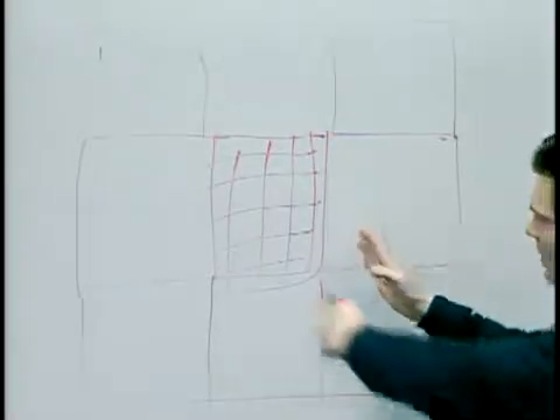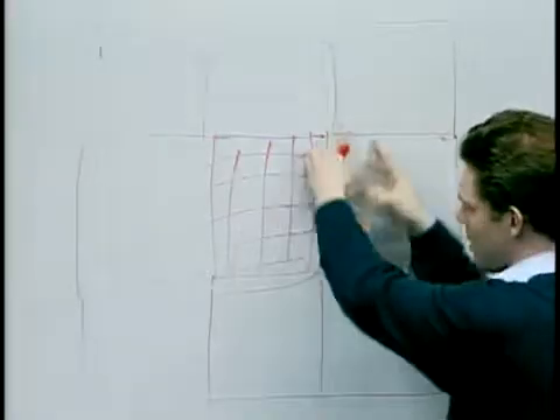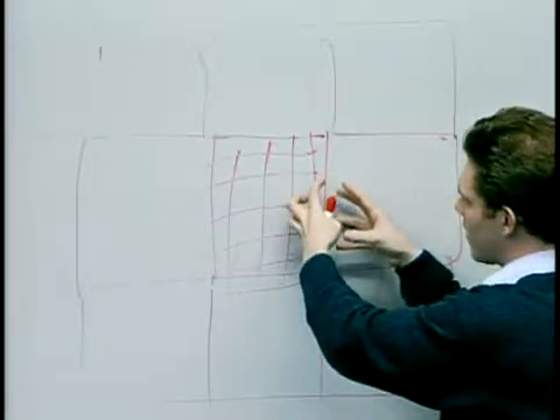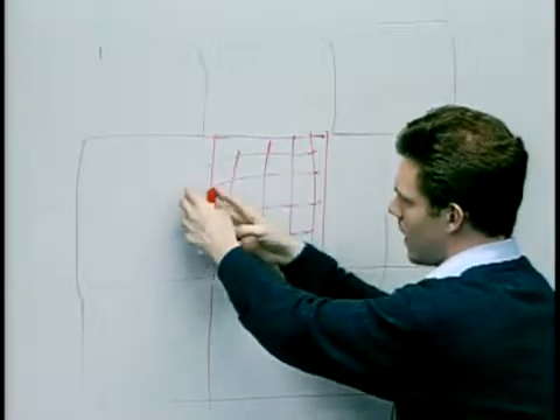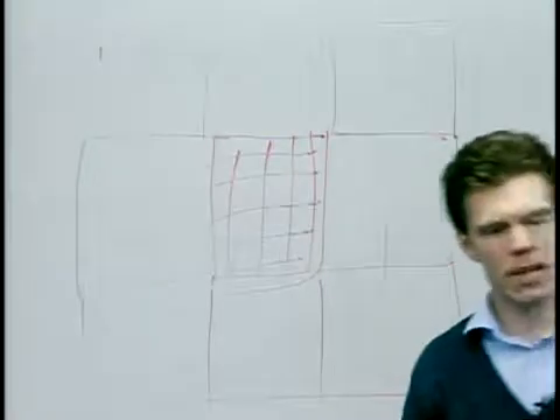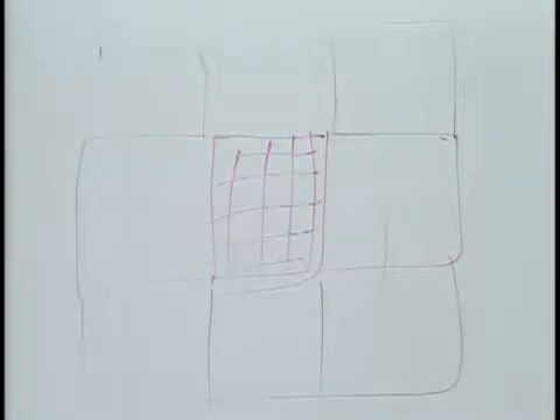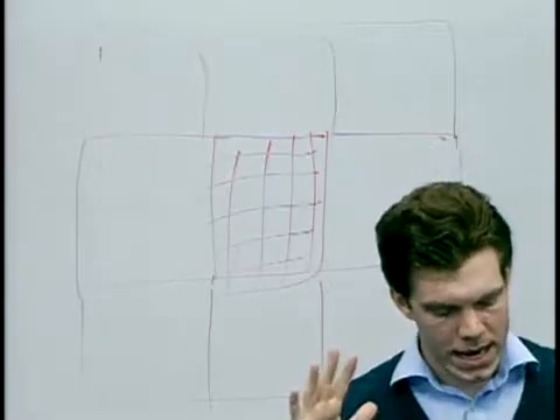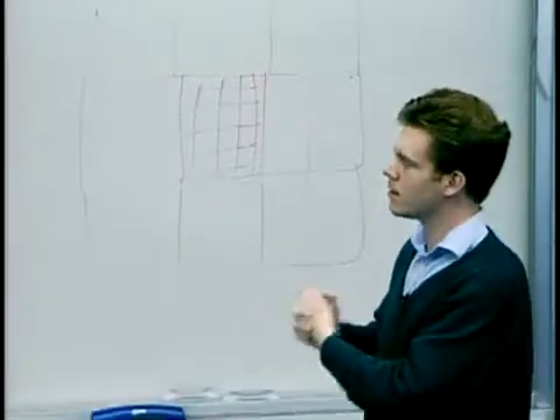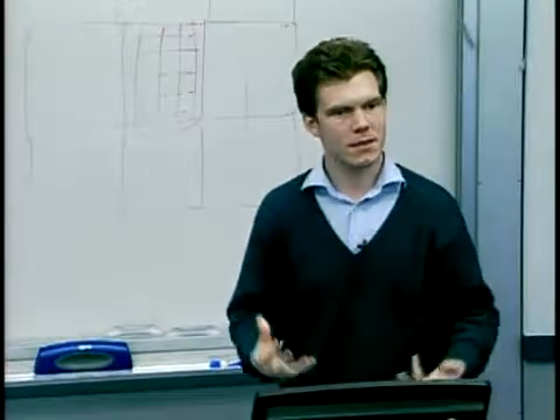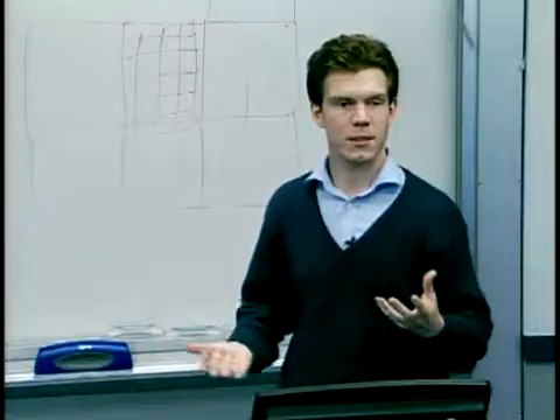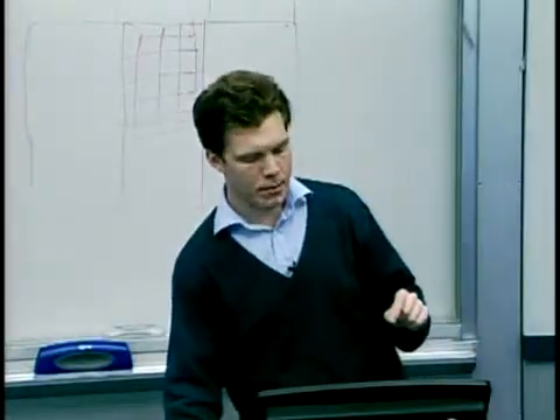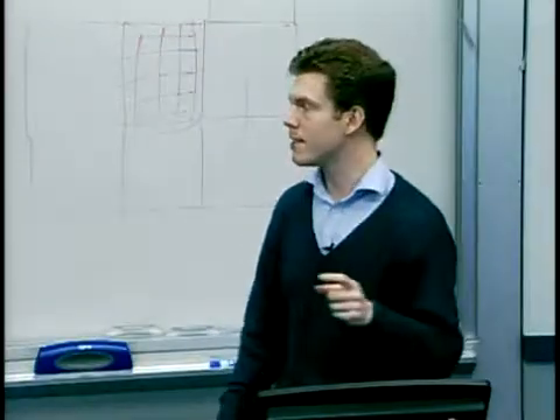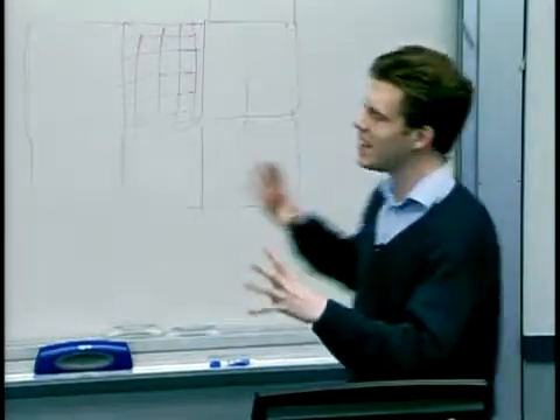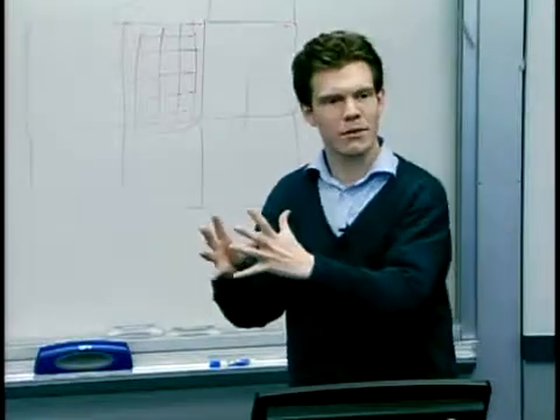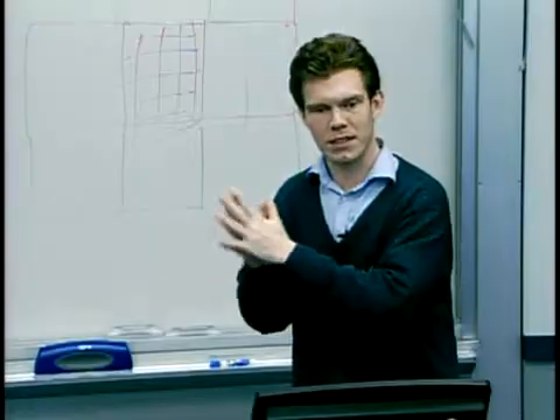The material's a millimeter thick. This is 4 millimeters. And so what's going on at the edge here looks exactly the same to the material as what this material sees over here. And that makes the simulation match up with the experiments nicely. So we etch this stamp, we choose some embossing conditions, press it into the substrate, and use white light scanning interferometry to measure the surface topography. The smallest features in this particular stamp are 5 micron in diameter. What we're also doing now is a set of experiments where we've scaled down this pattern 100-fold to make a nanoimprint lithography stamp of the same pattern.